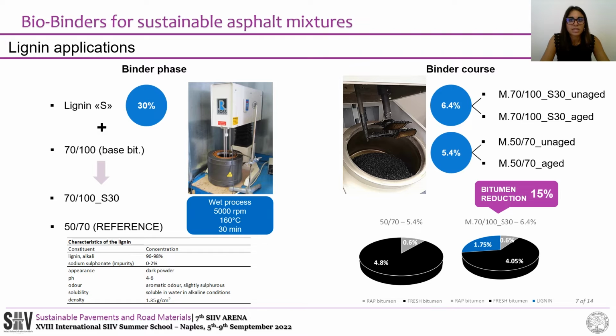The lignin content was optimized to obtain a biobinder characterized by a 50-70 penetration grade consistency, that is the most employed at Italian latitudes. For this reason, a 50-70 plain bitumen was selected as reference material. Even in this case, a high shear stirring mixer was used to produce the biobinder in laboratory.